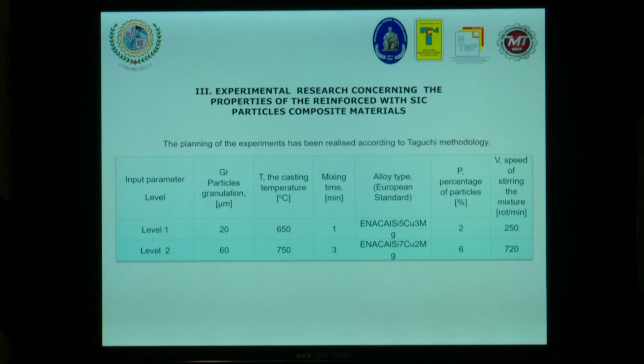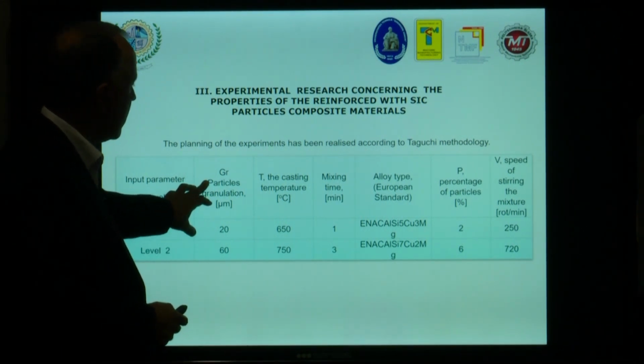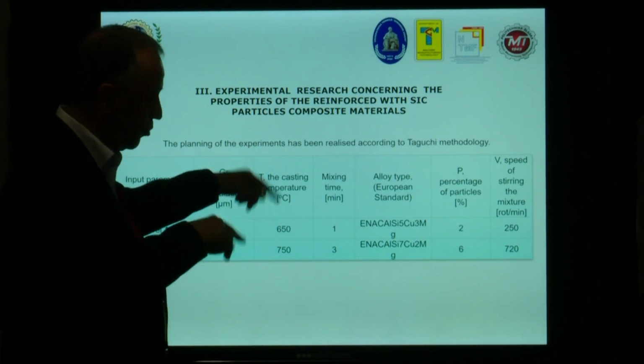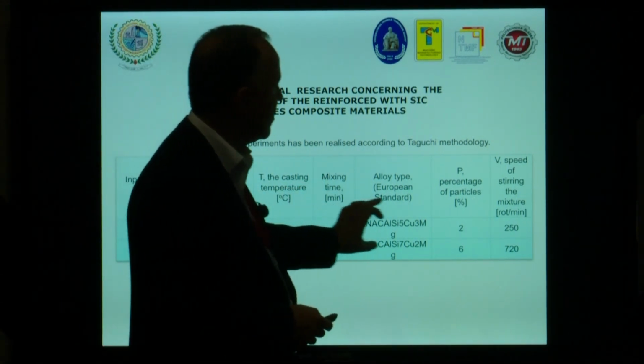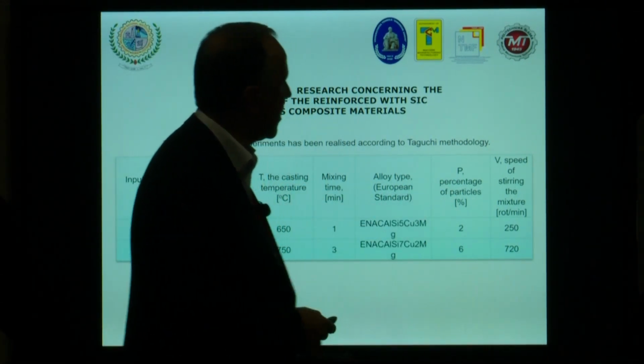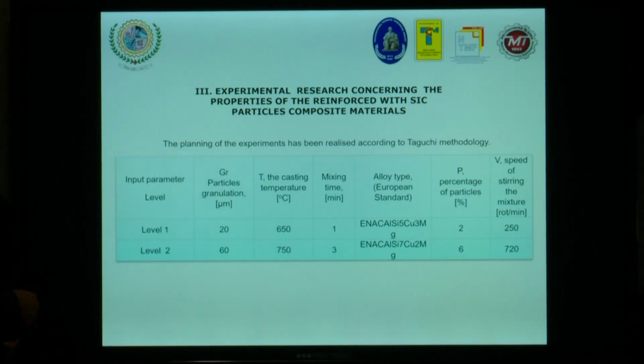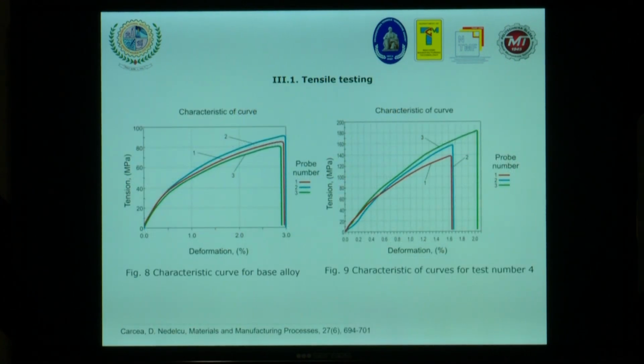The planning experiment: particle granulation, the casting temperature that we used, mixing time, and percent of the particle. And a little bit of results about the tensile strength.